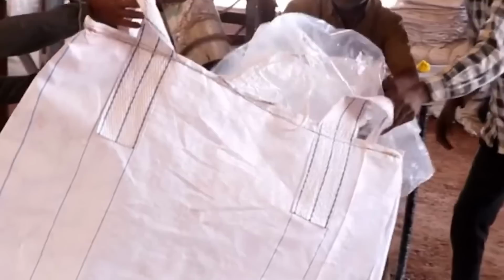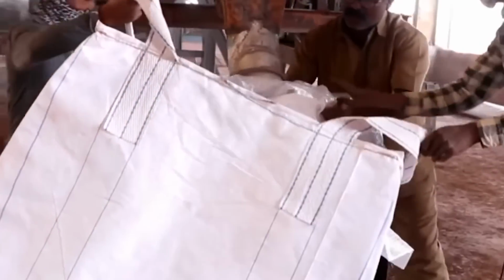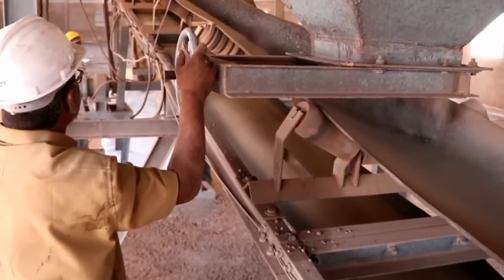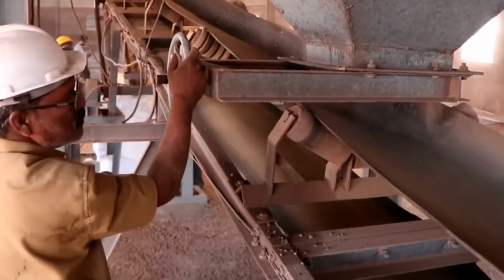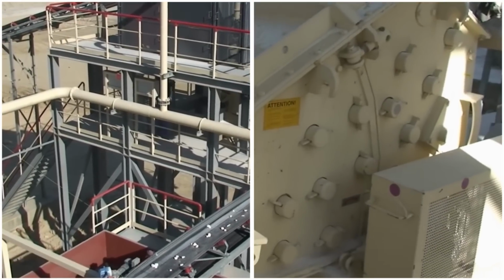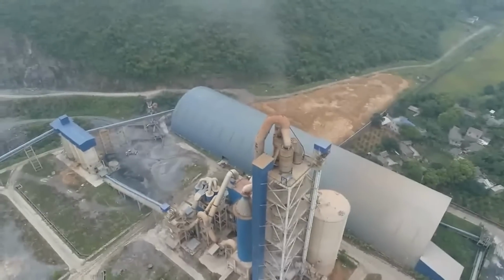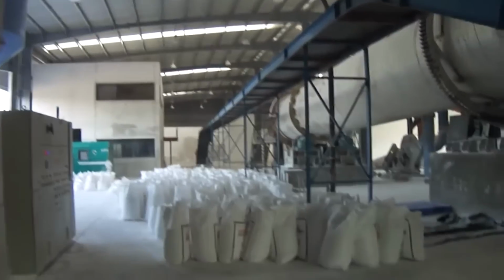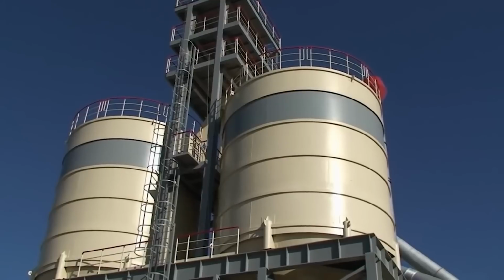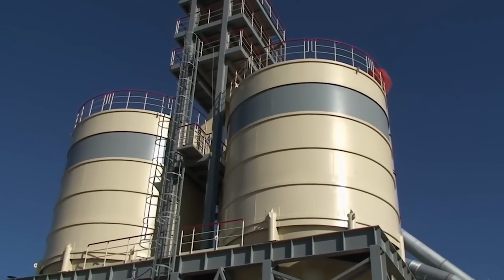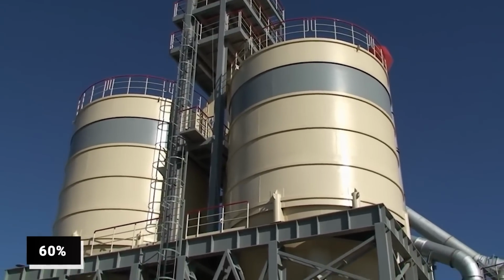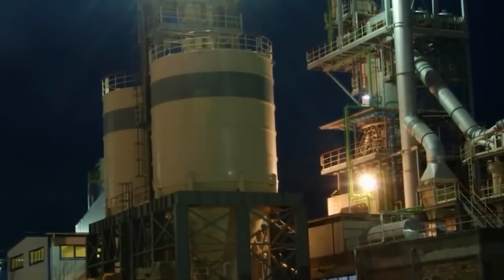One of the key reactions in the calciner is the decomposition of calcium carbonate, a primary component of the raw meal. This decomposition process converts calcium carbonate into calcium oxide and carbon dioxide. The release of carbon dioxide prepares the calcium oxide for further reactions in the rotary kiln. The calciner plays a vital role by handling approximately 60% of the total fuel burn, effectively reducing the thermal load